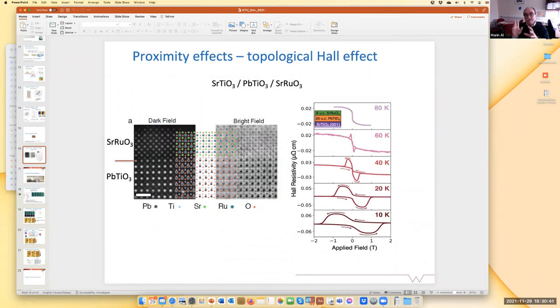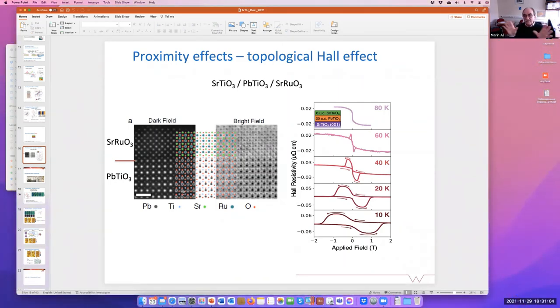And then they come back to a certain extent. But again, we have to mention that the studies they've been doing were in this superlattice type, when your ferroelectric is sandwiched between dielectric, between strontium titanate. And that is a completely different boundary condition. In our case, it's a metal, which is much more forgiving in terms of depolarizing field. Most of the depolarizing field is taken, nevertheless, by the metal. It's only the residual one which causes this swirling and all that structure which doesn't like lead titanate to have.